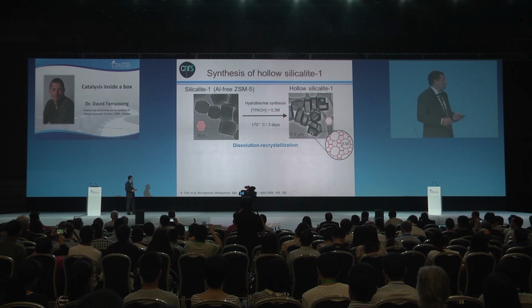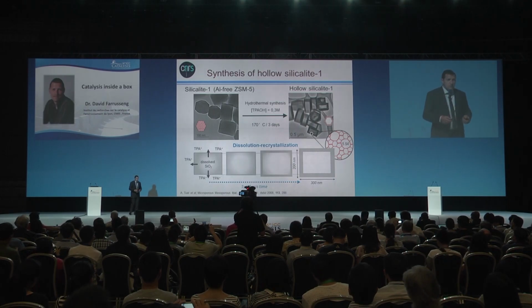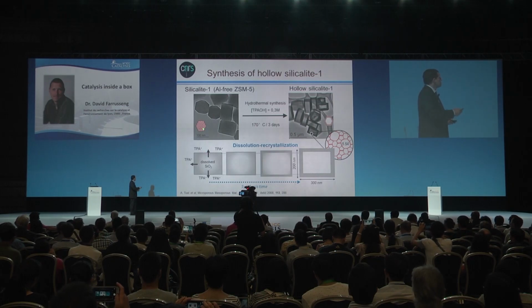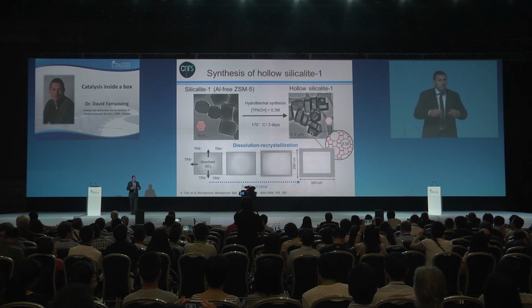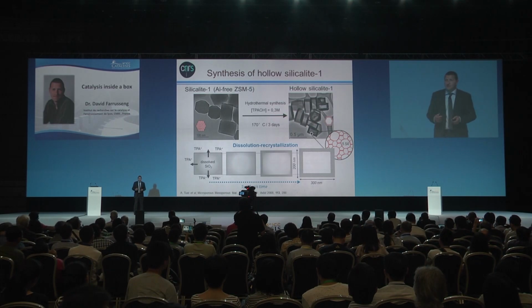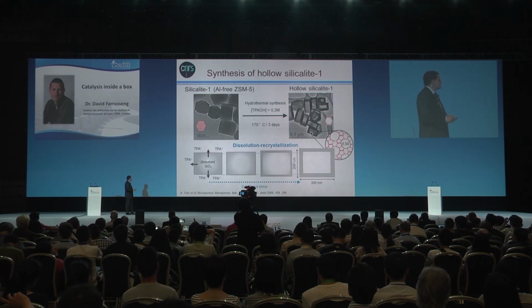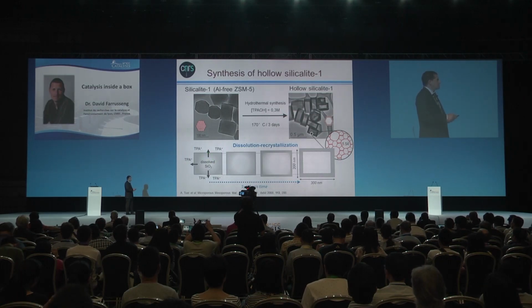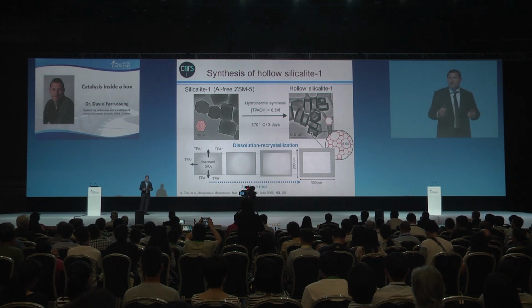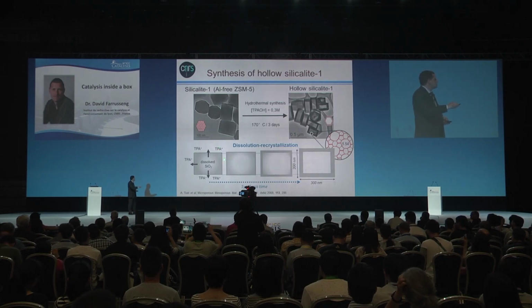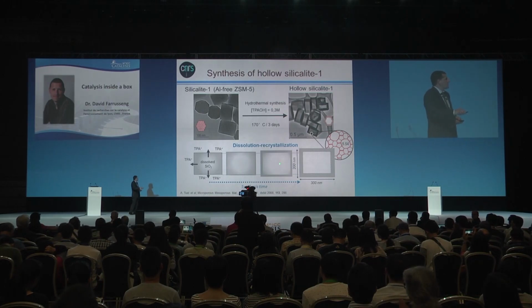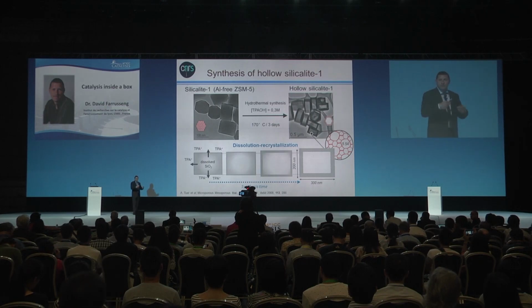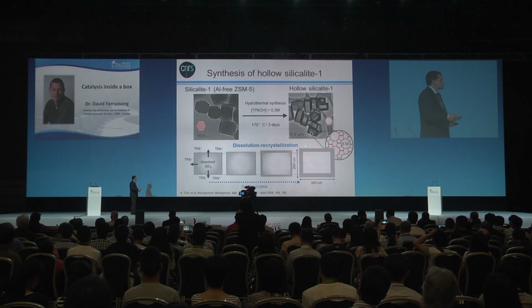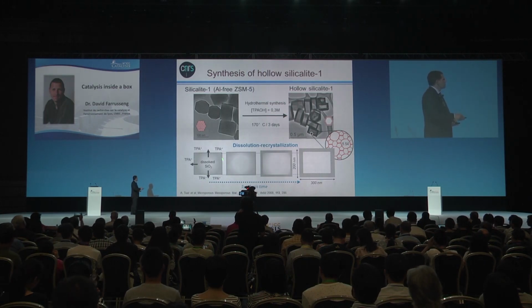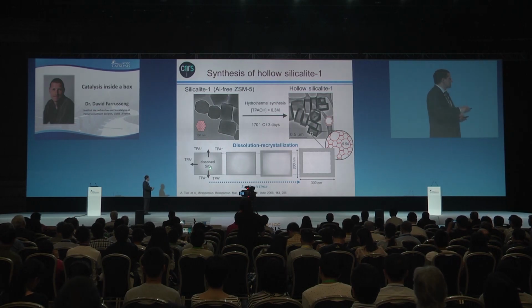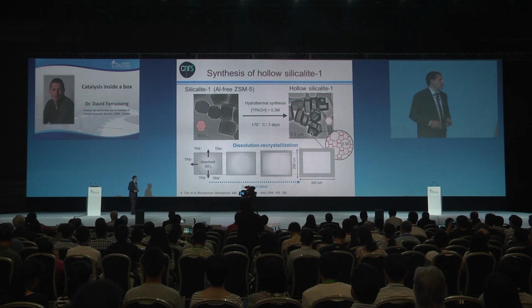When we saw that, we could hardly believe it. And I can give you the picture of the synthesis. We know that at the core of the crystals here, it's not so well crystallized, I would say. We have many silanol defects which are prone to dissolve in basic conditions. And when this silicate diffuses, eventually it goes to the surface, then it meets the tetrapropylammonium, which is the template which helps the crystallization, and immediately recrystallizes at the surface. And along with the synthesis time, you have less and less matter inside, and all the matter has been moved to the exterior and recrystallized at the interface, yielding a zeolite crystal which is a bit larger than the initial one. So here, 100% of the silicate which was inside has been recrystallized at the external surface.